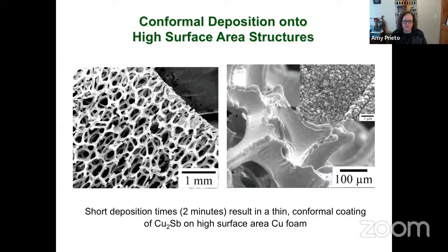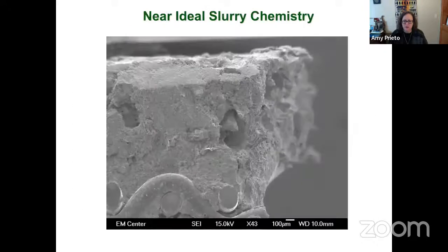This is a low magnification SEM image of one of the foams that's been coated with copper antimonide. You do see that there are thickness differences where there are areas of high curvature, and we worked really hard actually to smooth those out. You see cubic faceting when you zoom in, and that's indicative of the structure of copper antimonide. When we fully assemble the cell, this is a low magnification cross-section image. You see the aluminum mesh current collector on the bottom. And really what you're looking at is the spray-coated cathode over the whole battery.